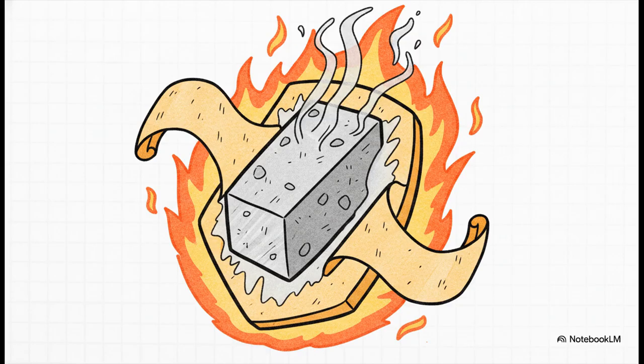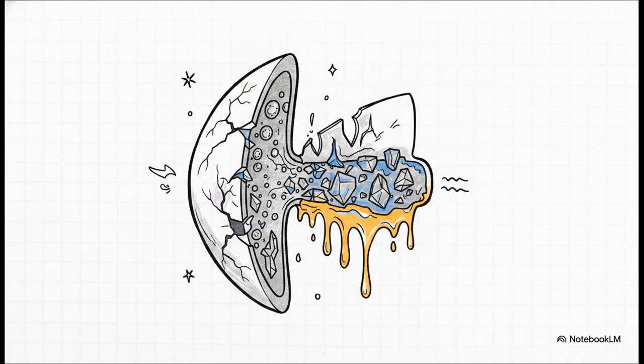It just volatilizes away into thin air, entirely losing its protective effect and leaving the raw carbide completely exposed to the harsh environment. And once that shield is gone, a completely devastating chain reaction kicks off. The exposed carbide undergoes rapid decarburization, turning into carbon monoxide and carbon dioxide gases, which literally blows microscopic pores into the material structure. The metal binder elements diffuse and form brittle intermetallic compounds.